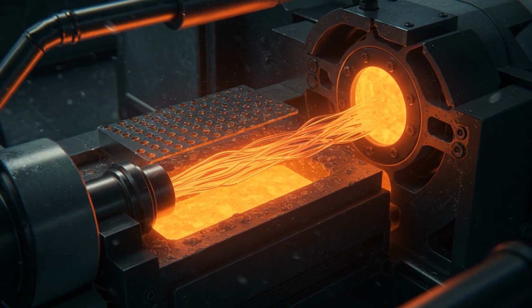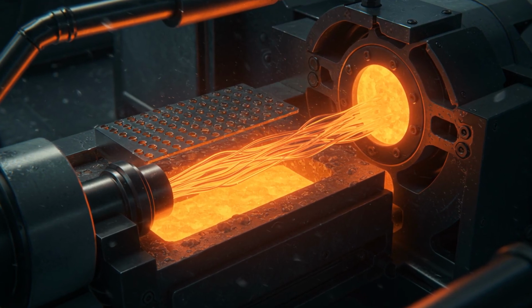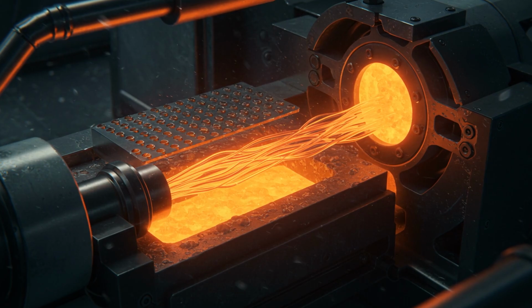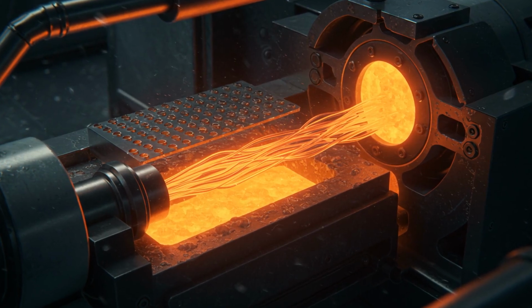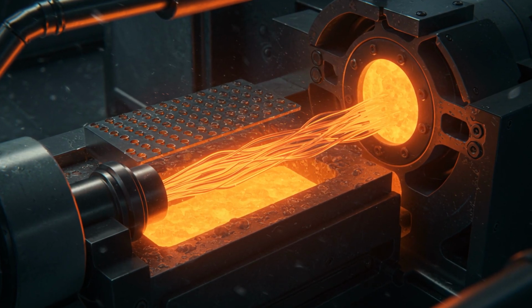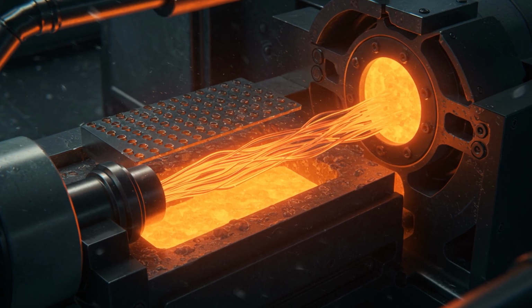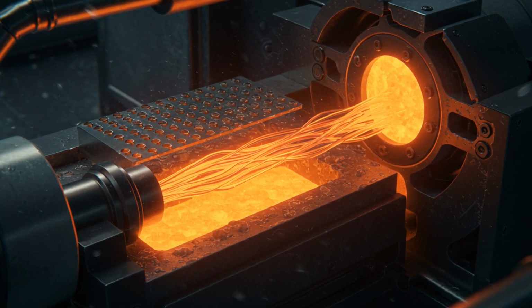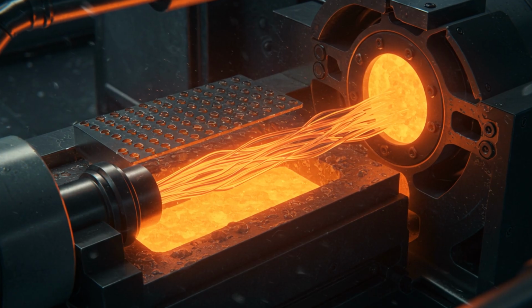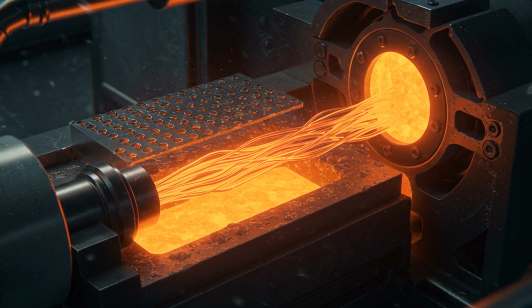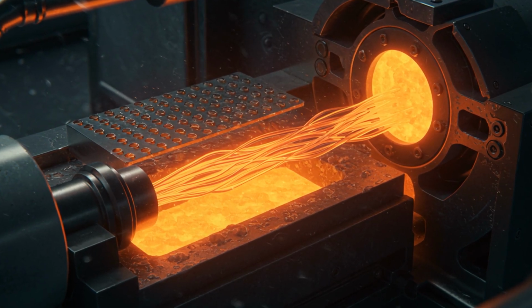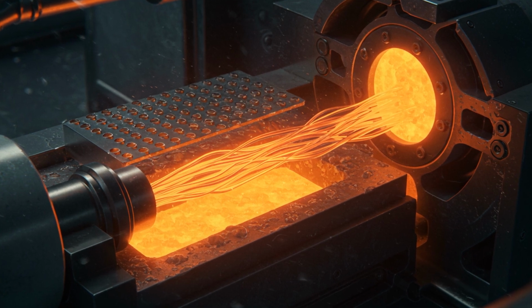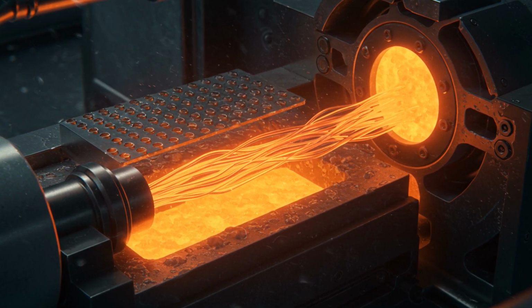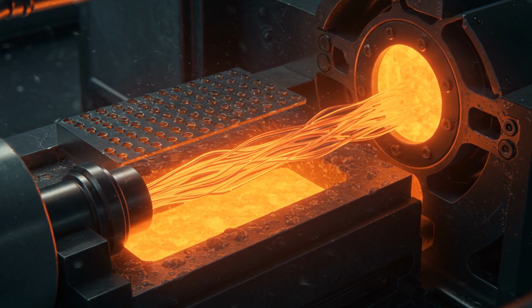Turning molten polymer into continuous fiber is a lesson in fluid mechanics and precision machining. The polymer melt is fed into an extruder, a heated screw that plasticizes and pressurizes the polymer. It is forced through a spinning pack and then through a spinneret plate, a hardened tool with hundreds to thousands of tiny holes. Each hole is typically in the range of 100 to 500 micrometers across. At 250 to 280 degrees Celsius, the polymer exits as molten jets.